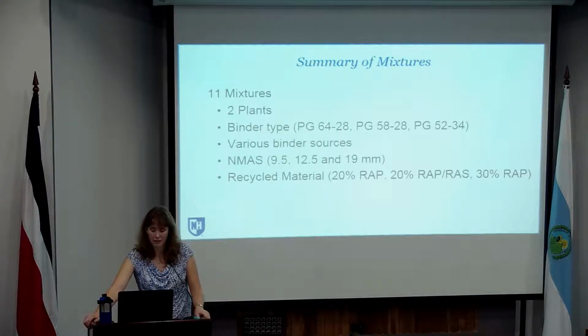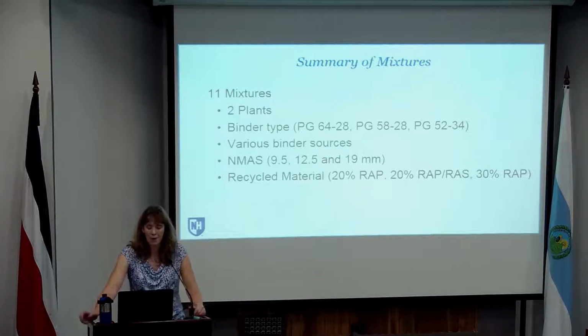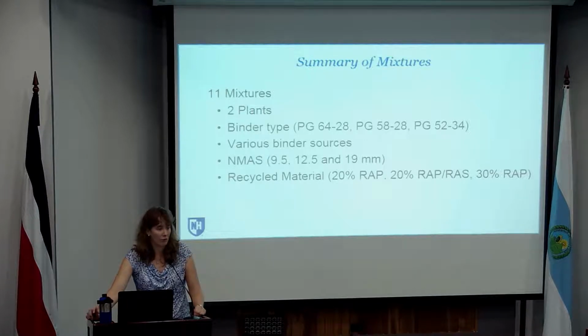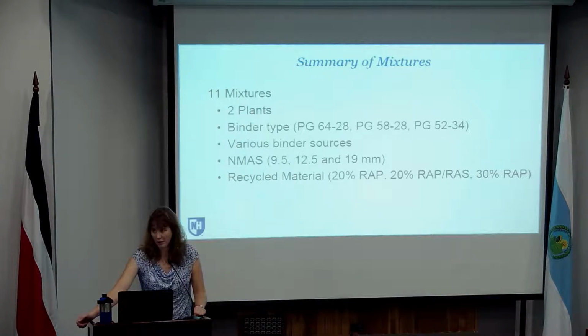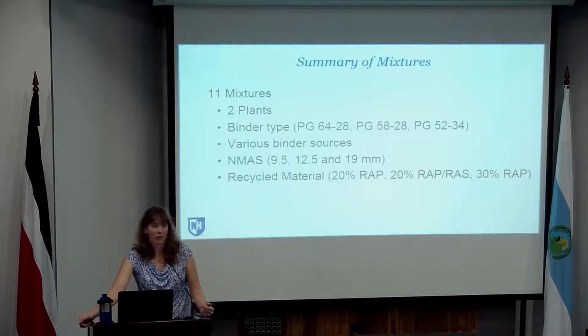Okay, so we looked at several different binder sources for some of these, different aggregate gradations, okay, relatively fine to relatively coarse mixtures, and then looked at different recycled material components. So from 20% RAP by total weight of the mix up to 30%, and then also 20% combination of recycled asphalt pavement and recycled shingles. Now, this is the first time that New Hampshire DOT had actually produced mixture and put it down in a state project with shingles. So this was kind of a big deal.